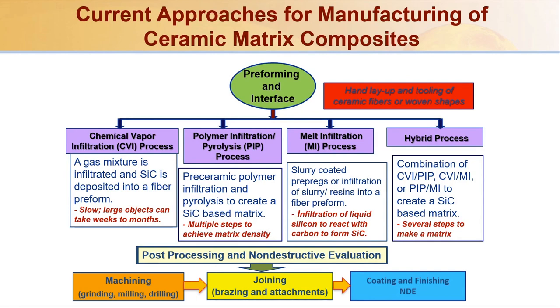So obviously everything starts with making some type of preform and applying the interface. And then in terms of the matrix densification, either you use the chemical vapor infiltration process, which is fairly slow, and large objects can take weeks to months. Or you do the polymer infiltration and pyrolysis process, where you typically have multiple steps to achieve a dense matrix. Or you do the melt infiltration process, where you basically infiltrate silicon or some silicon-based alloy and react with carbon to form silicon carbide plus other refractory carbides or silicide phases.